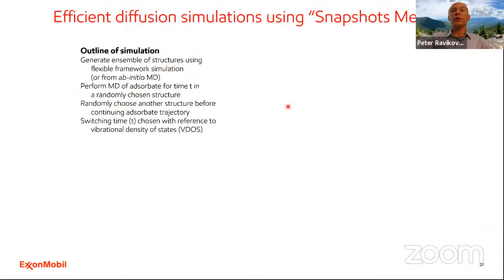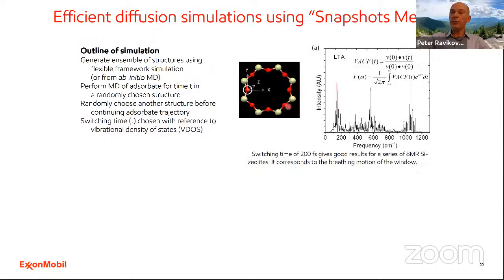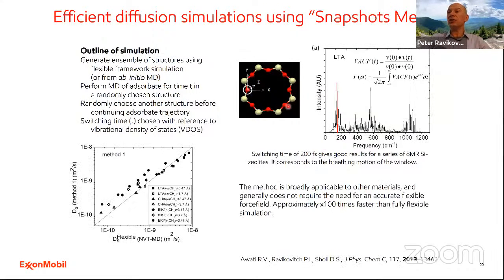Another way of simulating flexibility in zeolites in a more efficient way is to use the so-called snapshot method. In the snapshot method, instead of doing simulations with the flexible structure, what one can do is simulate the empty structure and take snapshots, and then use these snapshots to perform molecular dynamics simulations with rigid structures and periodically replace the snapshots.